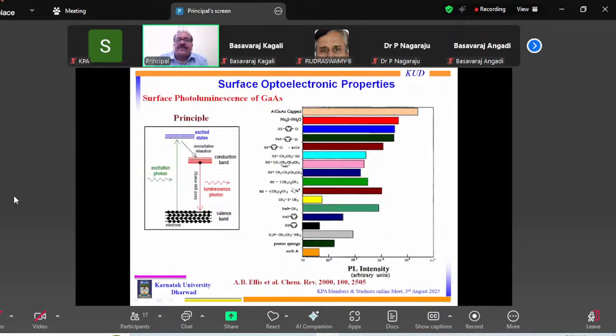So just to have a feel about this, I have taken from the literature how molecules can modify the surface photoluminescence of gallium arsenide, a very well-known semiconductor. What people have studied is how surface attachment by organic molecules can affect the surface photoluminescence. What you see is a bare, just etched gallium arsenide. You have the photoluminescence signal up to this. By putting various molecules, you can try to tune, and finally you have the aluminum gallium arsenide.